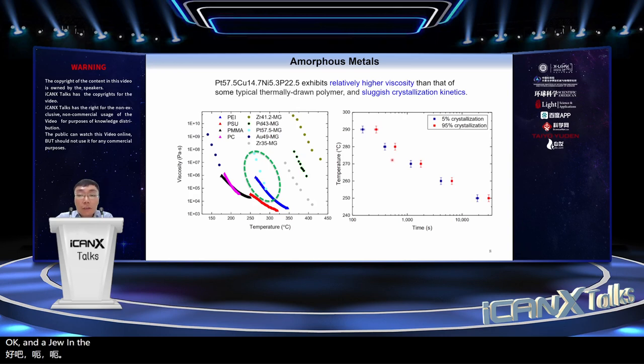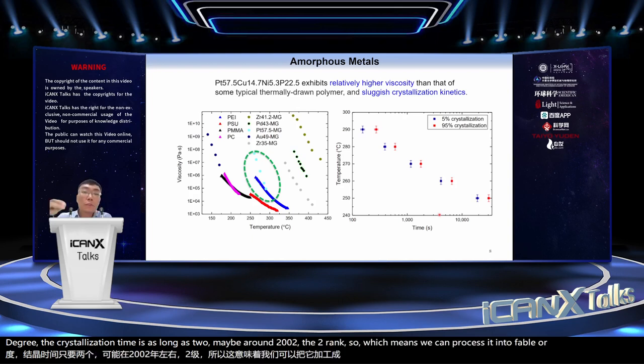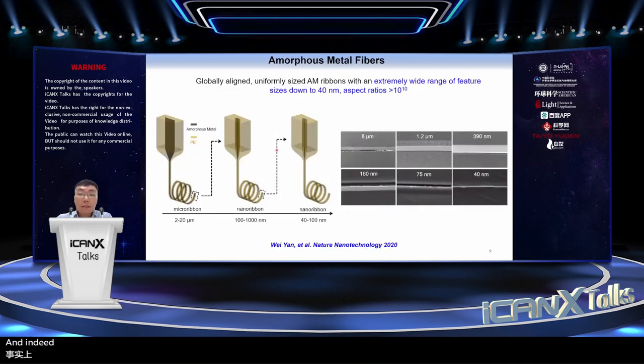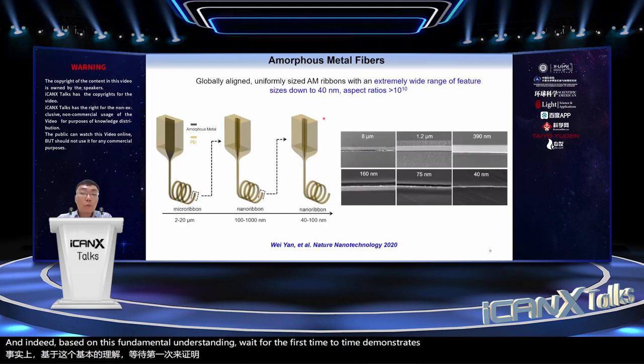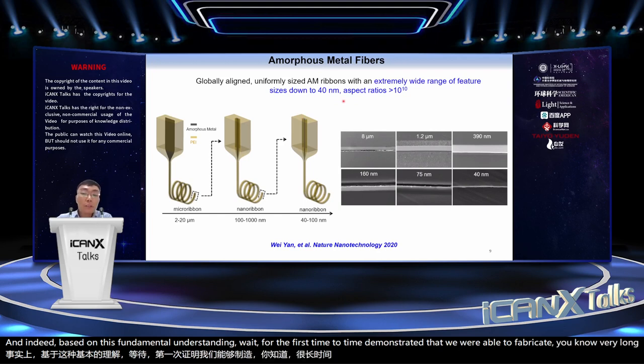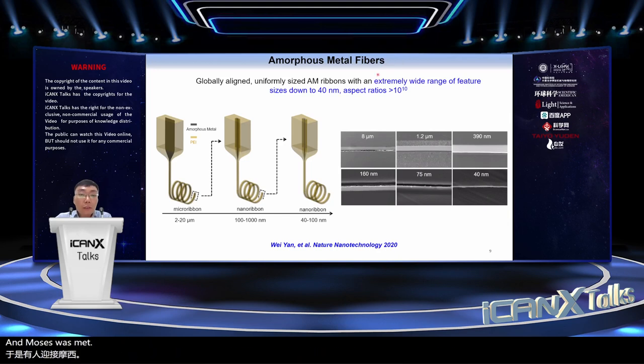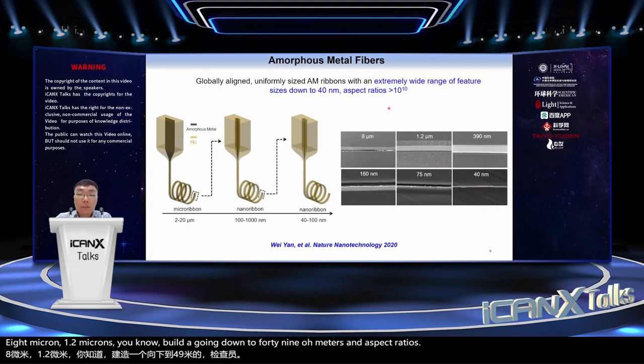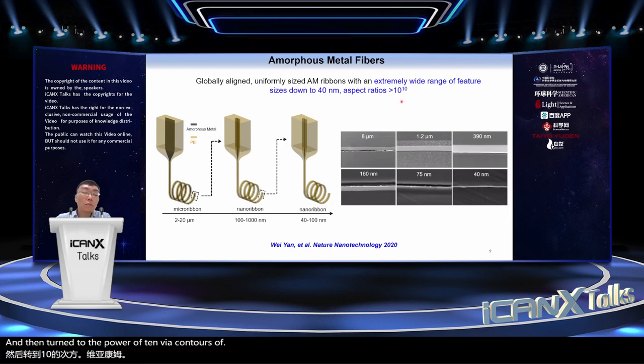And during the supercooled liquid region, we can see that the crystallization kinetics of this material is also very sluggish. Okay, for example, at 260 degrees, the crystallization time is as long as maybe around 2,000 seconds, right? So which means we can process it into fiber before the material becomes crystalline, okay? And indeed, based on this fundamental understanding, we for the first time demonstrated that we were able to fabricate very long, uniformly sized amorphous metal fibers with an extremely wide range of feature sizes. You know, we can reach 8 micron, 1.2 micron, going down to 40 nanometers and aspect ratios greater than 10 to the power of 10 via control of the viscosity ratio of the two materials.